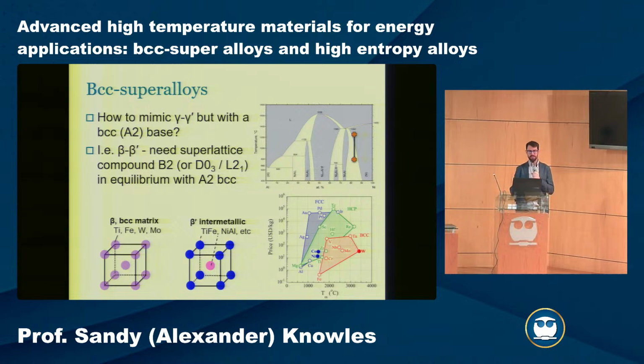And then we need to think, okay, we've changed the crystal system of the matrix phase, so we also need to change the crystal system of the intermetallic reinforcement. Luckily, there are a large number of intermetallics that do have an ordered BCC crystal structure. For example, nickel aluminium or titanium iron both have this ordered BCC-like symmetry, which could potentially be a superlattice compound for a BCC matrix.